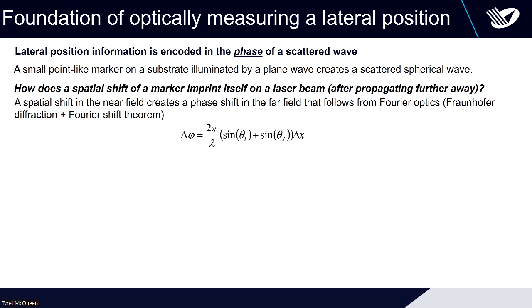So you basically get any position shift here as a phase shift. And already in the previous example, I showed we can measure phases from interferometric techniques or from some tricks with gratings with a very high accuracy, because we can just translate that to intensity measurement. So that's where the sensitivity comes in. It's not a resolution. You're not going to see a 5 nanometer pitch grating with it, but you can determine if a 10 micron pitch grating is aligned with an accuracy of 5 nanometer. That is the trick here.